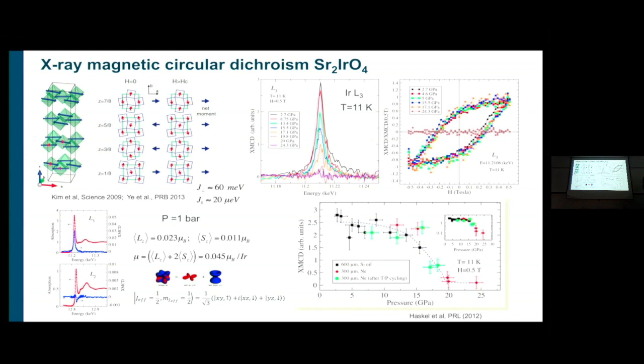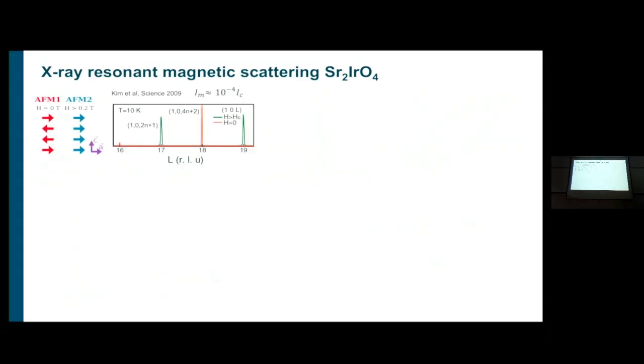And you say, well, look, XMCD is only sensitive to the net magnetization. But that's this little canted moment because of the octahedral rotation. What if the octahedra are no longer rotated? What if pressure removes this rotation, and now you have a perfect antiferromagnet with no net moment? It's a G-type antiferromagnet. So you want to measure resonant magnetic scattering. And the interesting thing here is that this is the zero field canted moments as you go through the layers, left, right, left. And if you apply a magnetic field, you get this.